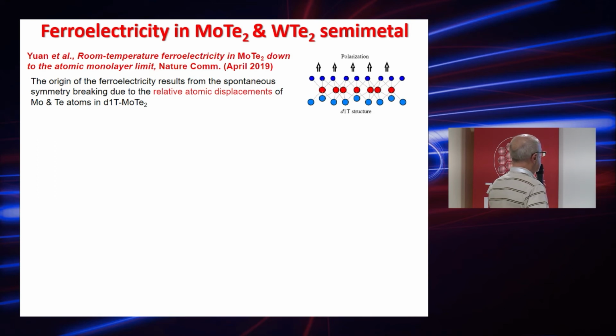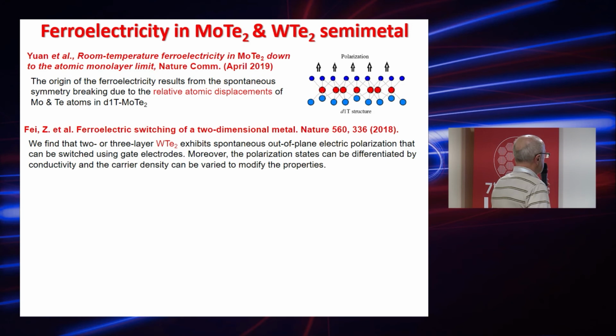In a paper published by Yuan with the title Room Temperature Ferroelectricity in Molybdenum Ditelluride down to the atomic monolayer limit, they concluded that the origin of the ferroelectricity results from the spontaneous symmetry breaking due to relative atomic displacement of molybdenum and tellurium atoms. In the next paper by Fei, with the title Ferroelectric Switching in Two-Dimensional Metal, they found that 2 or 3 layer tungsten ditelluride exhibits spontaneous out-of-plane electric polarization that can be switched using gate electrodes. Moreover, the polarization state can be differentiated by conductivity, and the carrier density can be varied to modify the properties.